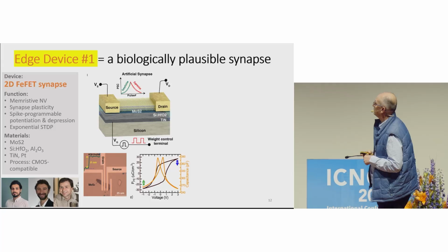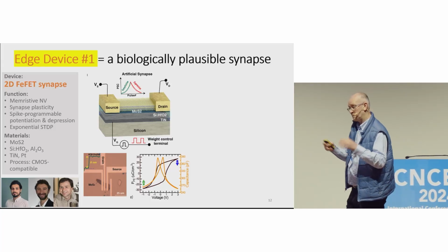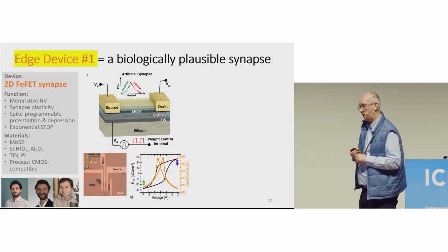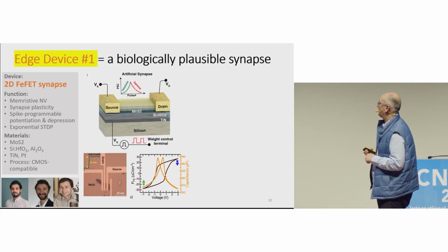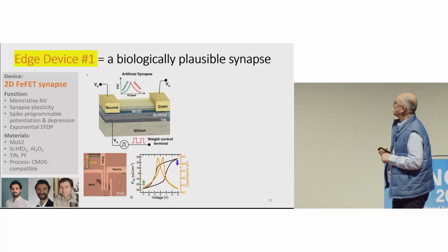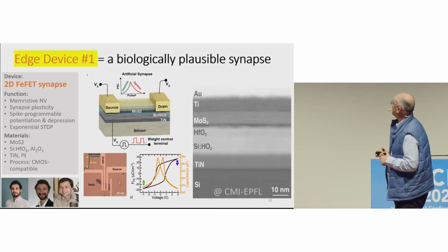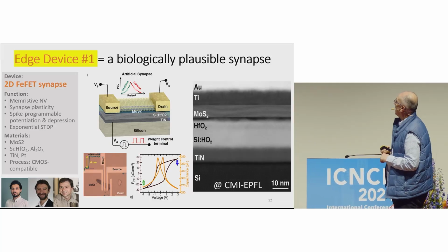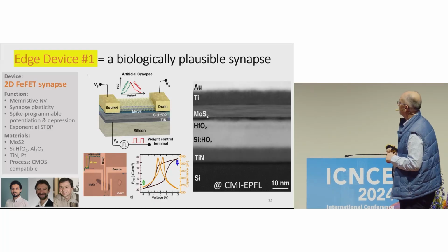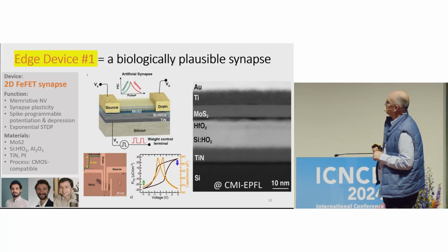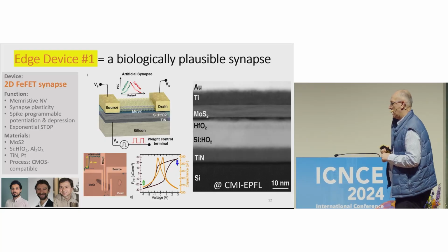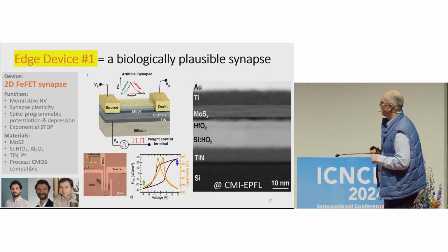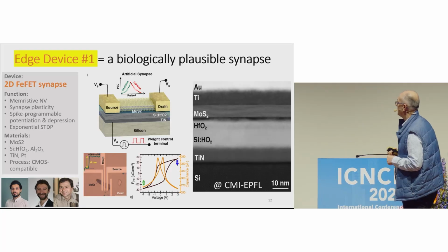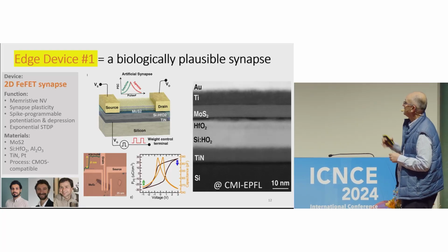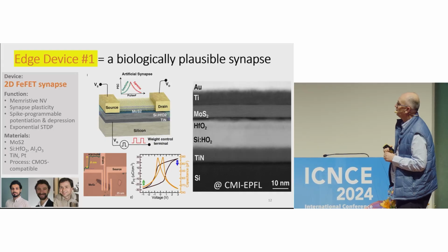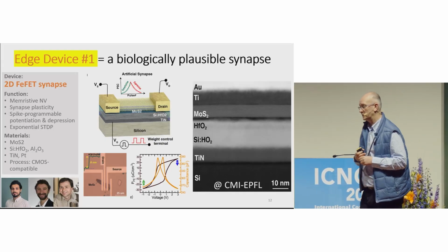So the first thing we had to do was to develop a very clean, effective stack where we have a certain quality of the ferroelectricity with low leakage. So we were using practically silicon doped hafnium oxide. Sorry for the typo there, hafnium oxide. So we can get a remnant polarization between 15 and 20 microcoulomb per centimeter square with a relatively small coercive field, which will let us operate this device at few volt and potentially scalable below 2 volt.